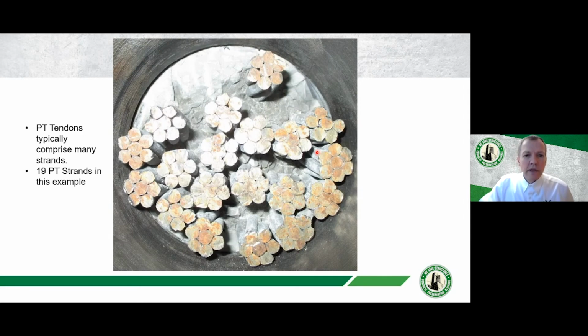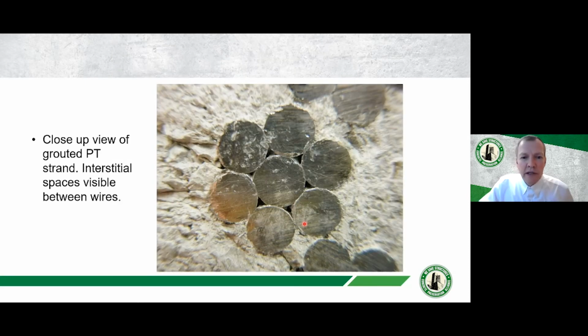In a typical tendon, you may have a number of strands. In this case, I think there's 19 strands, and those strands are grouted in, hopefully fully grouted into the duct, so that there's no real space or voids outside of the strands themselves. If we take a close-up view of the end of one of those strands, you'll see we have 6 outer wires. We have an inner king wire, and in between the wires here, we have what we refer to as interstitial spaces. And these are effectively longitudinal capillaries that run the full length of the tendon. And that's where the material is primarily traveling, along the length of these capillaries.